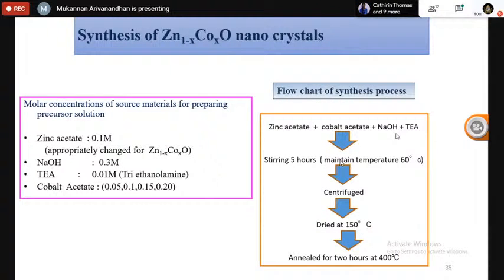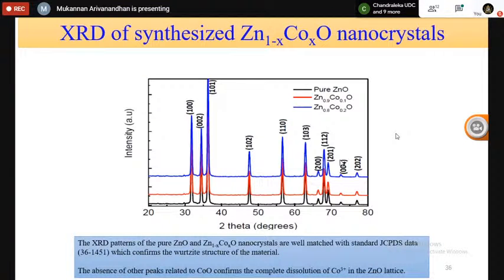So instead of aluminum, we have tried with cobalt, and the protocol is almost the same. And look at the pattern. The pattern is quite stable, identical, up to 20% of cobalt, unlike the aluminum substituted system. So the cobalt is completely dissolved in the zinc oxide lattice due to the high solid solubility limit of cobalt.